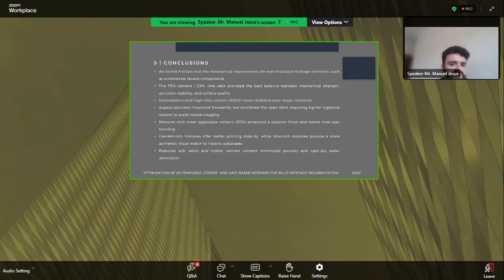Mixtures with lower aggregate content produced a superior finishing also and better bonding between the layers, and cement-rich mixtures offered better printing stability, while lime-rich mixtures provided a more aesthetic visual match to the historic substrate. Also, the lower water-to-binder ratios and the higher cement content minimized porosity and capillary water absorption.